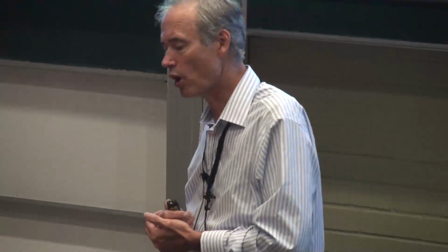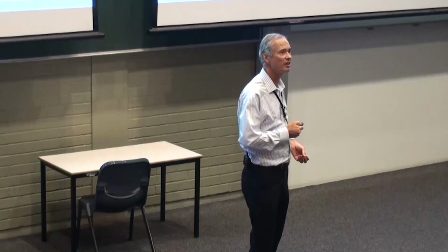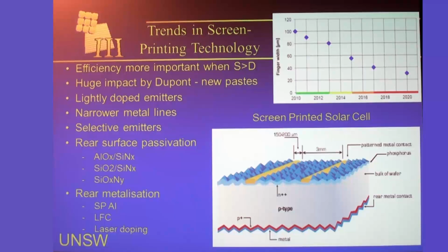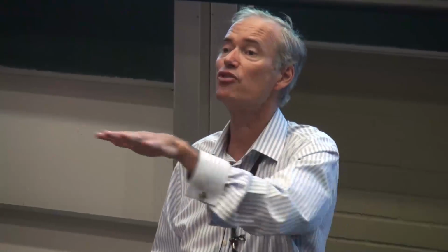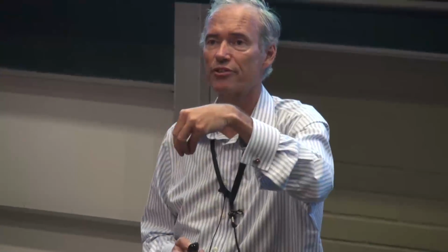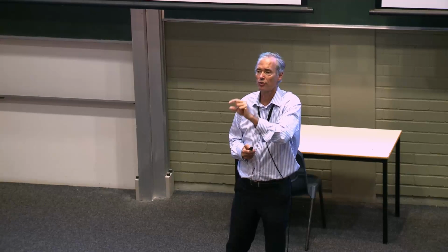So talking to quite a few companies, they've said similar things, and that is that with all the recent developments by DuPont that I've already mentioned, it takes away a lot of the importance of wanting to go to a selective emitter structure. For those that aren't aware, selective emitter simply means you put heavy doping directly under your metal, which solves the contact resistance problem, but you then have lightly doped emitter over the rest of the area, which is where the light penetrates through. But the problem, of course, is that you then have to align your metal to those heavily doped regions. And so manufacturers in general would prefer a self-aligned approach.